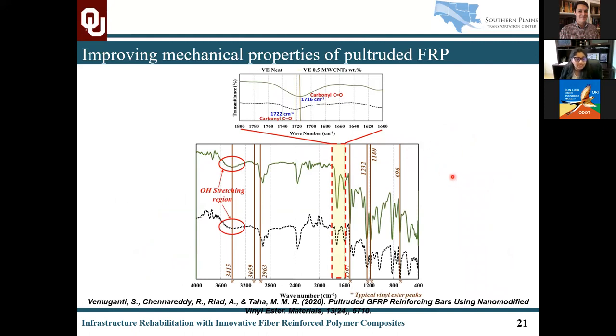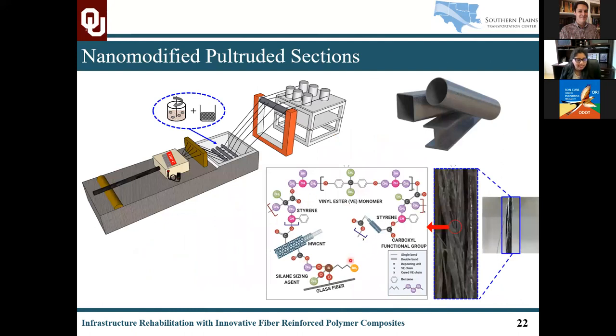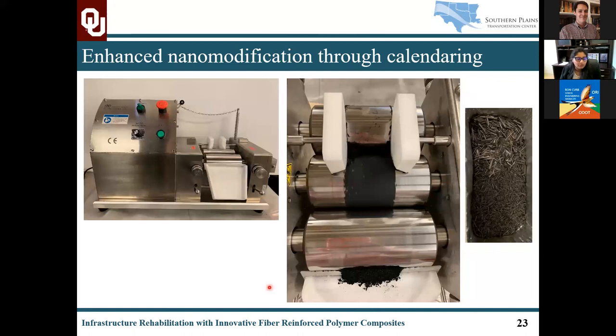So confirmations of these studies included Fourier transformation infrared analysis to understand what kind of chemical changes were seen in this kind of nanomodification, how the nanotubes are reacting with the resin, but also how these nanotubes are reacting with the agents on the FRP itself, the silane sizing agents, and how they form the bonds with the carbon nanotubes, resulting in better enhanced bonds. So we see definitely a lot of future in the nanomodified pultrusion in terms of producing sections, in terms of also enhancing this nanomodification process.